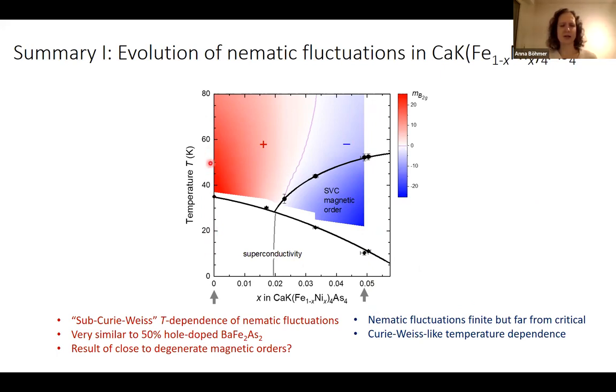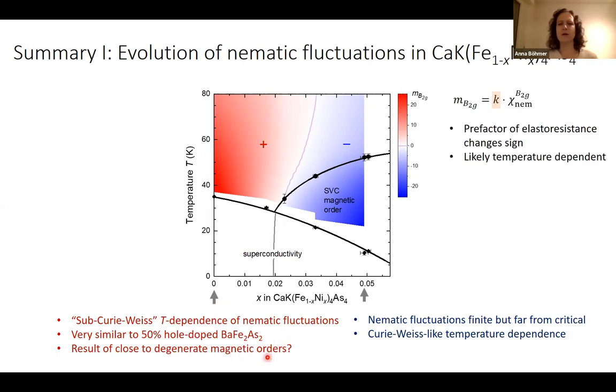On the optimum Tc sample, it's very similar to the hole-doped 1-2-2, the equivalent one. And we think that might be a result of the magnetic order being close to the transition line between the SVC phase and the stripe-type phase. Overall, most striking is that we have an example where the prefactor of the elastoresistance changes sign in a composition-temperature phase diagram, and also becomes likely temperature dependent, at least in a part of this phase diagram.